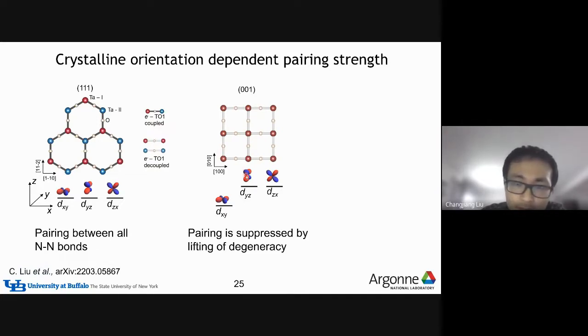And also, this is because of the quantum confinement, the dxy orbital has the lowest energy. So there's a splitting between the dxy and dyz, dxz orbitals. So there's only one orbital left in the lowest energy. So then the hopping between these orbitals is suppressed by the lifting of this degeneracy. So this explains why the pairing or the superconductivity is very weak for this KTO-001 surface.